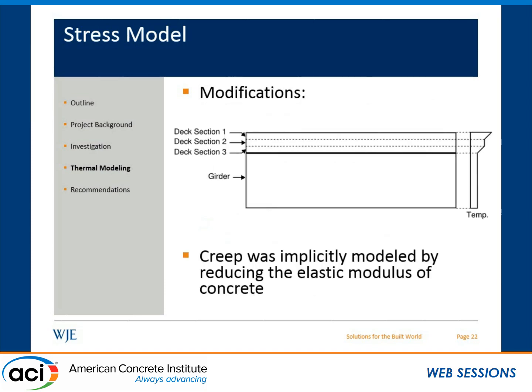We took that a little bit further, and we split the deck into 3 sections because we wanted to be able to model the effective temperature gradients that are more complex than just a uniform temperature change or a linear temperature change. So we divided the deck into 3 sections, but the same principles applied. We used compatibility at all of the interfaces to calculate the stresses that were generated. And we also modified the model by incorporating creep into the model. And this was done implicitly. We basically assumed that at very early ages, the elastic modulus was half of what it actually was.